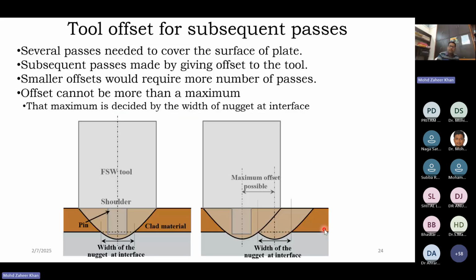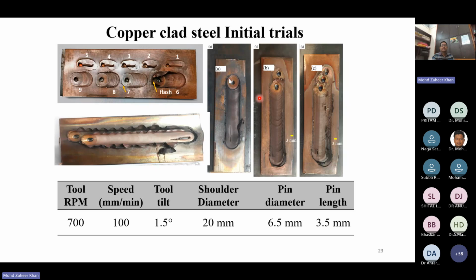Now, as I have mentioned earlier, when we are performing this cladding operation, then in one pass, only a certain portion of the material could be cladded. Like this is a plate of mild steel, and there is a copper on top of it. And if one pass is there, then only from here to here, up to this width only, some amount of bonding has taken place between the copper and the substrate. Whereas the remaining portion has not been bonded.